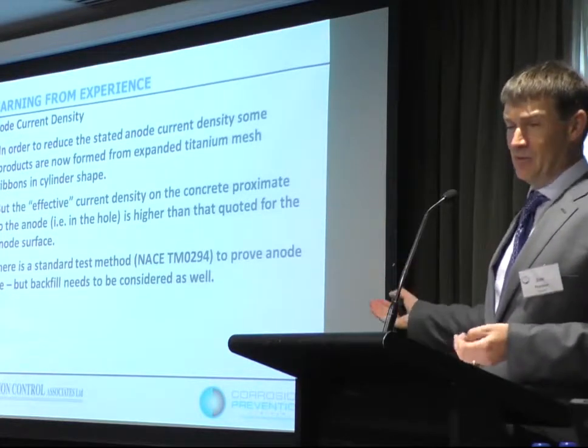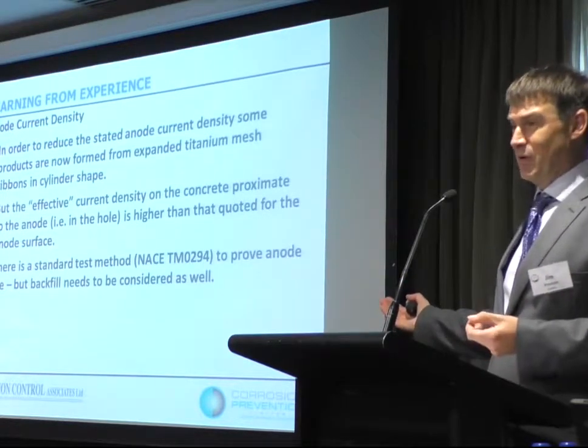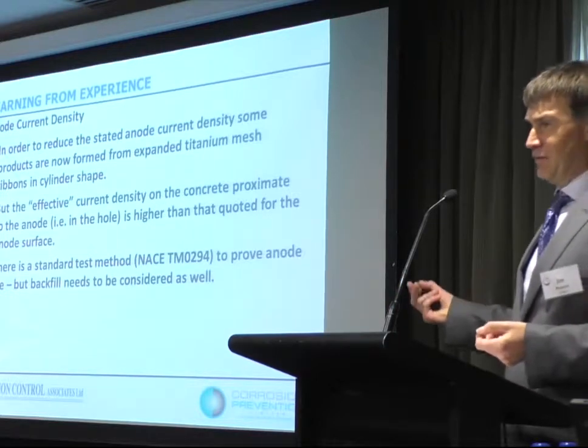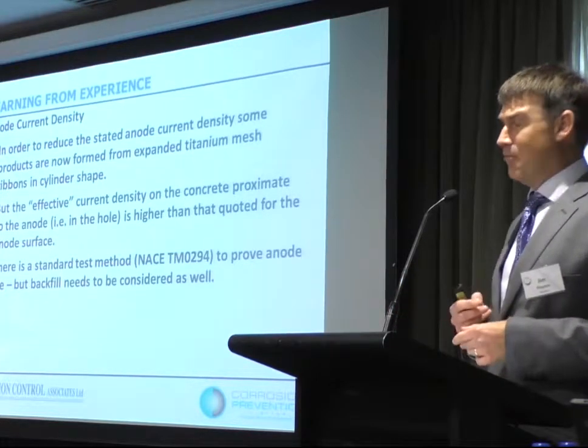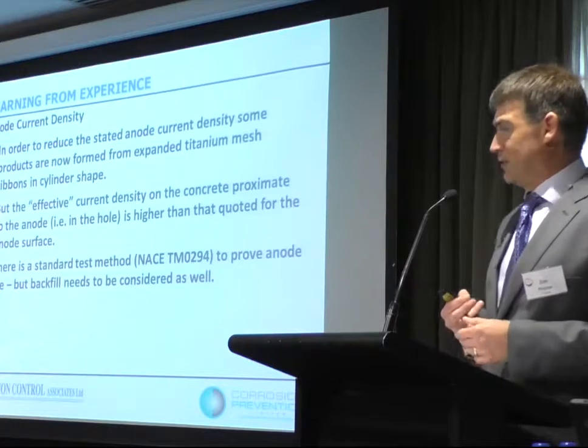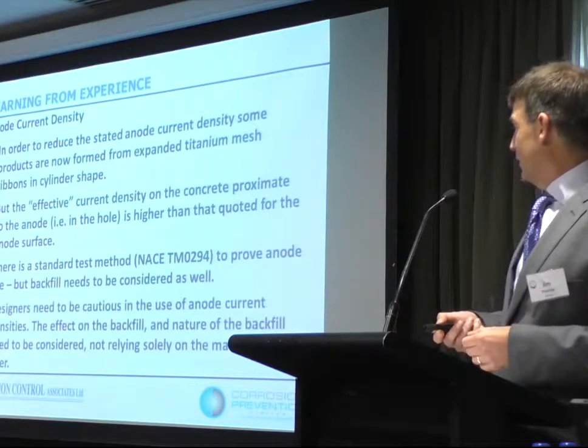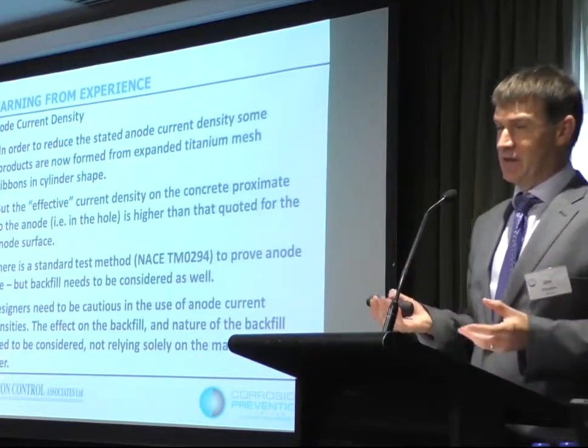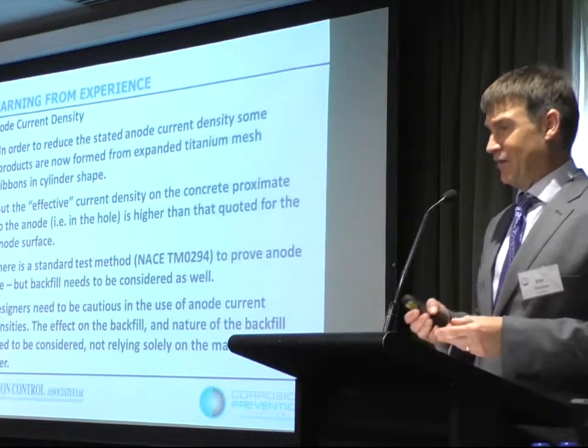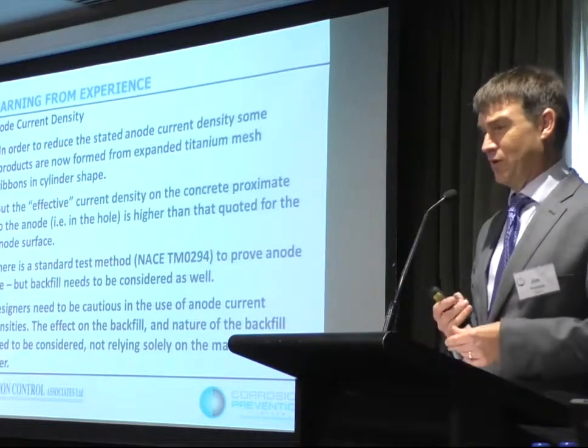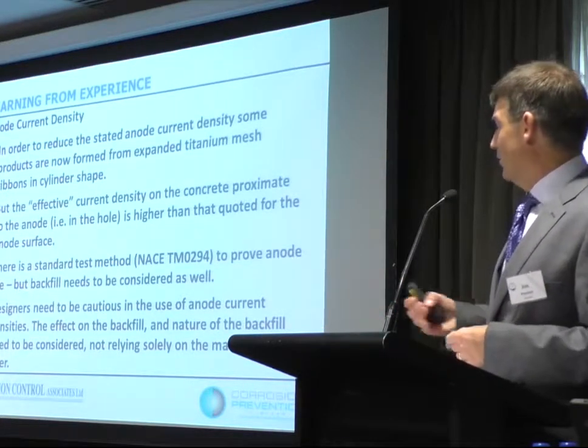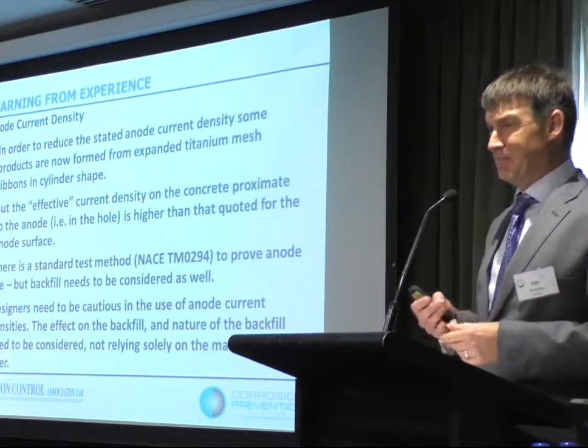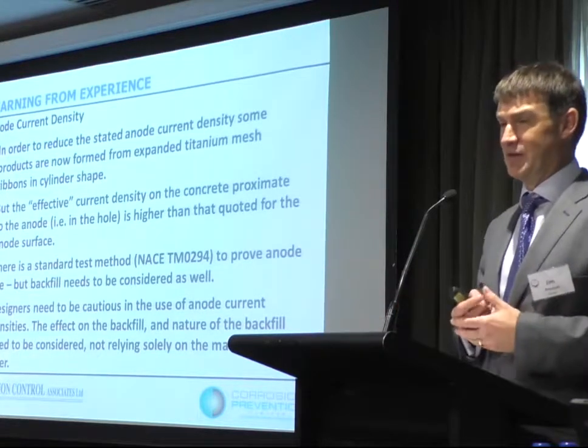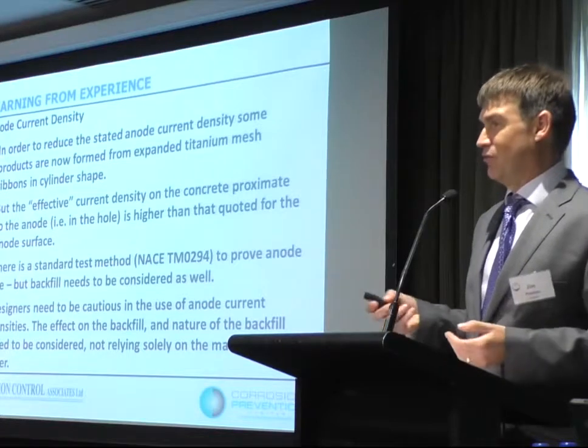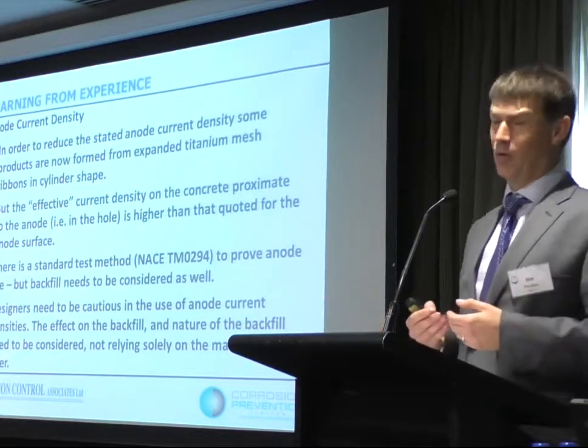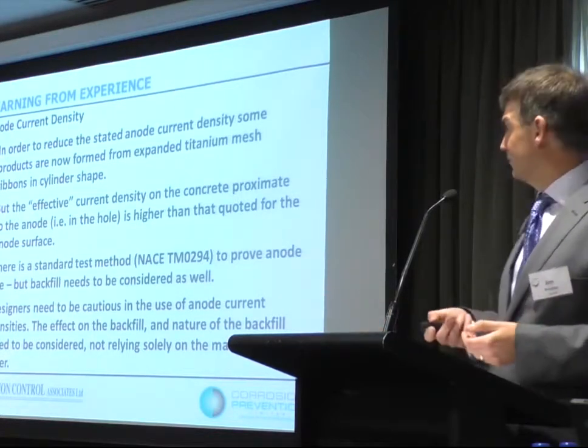We can test the anodes. We don't really see any issues with anodes. We don't see anode failures. It's a very, very rare thing. The anodes could be proven to last for the life we need. But as designers, we just need to be cautious in what we're designing, have a think about the backfill materials, the property of it, the depth of cover, and can we maximize the life of the system by reducing the anode current density by having longer anodes or bigger diameter anodes.